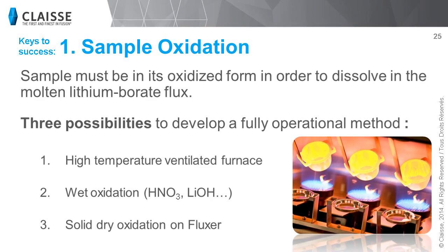As mentioned at the beginning of this presentation, only oxides are dissolved in the molten borate flux. However, semi-oxidized samples or non-oxidized samples can also be prepared by fusion. They only require proper oxidation steps prior to fusion. The fastest and easiest way to perform this oxidation is to do it directly on the fusion instrument. The most commonly used oxidizers for the solid dry oxidation on a fluxer are lithium, sodium, and ammonium nitrate. Carbonates and other oxidizers can also be used.